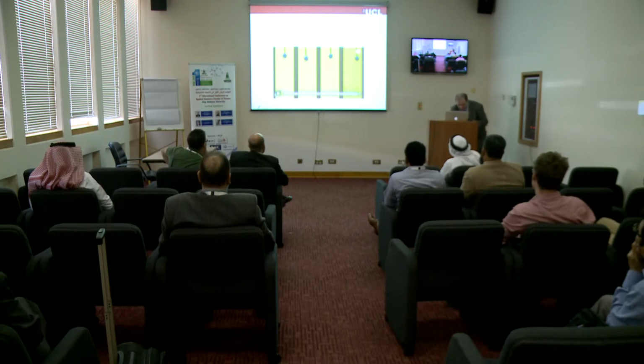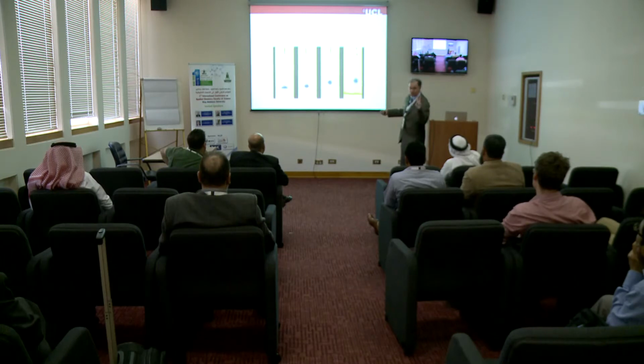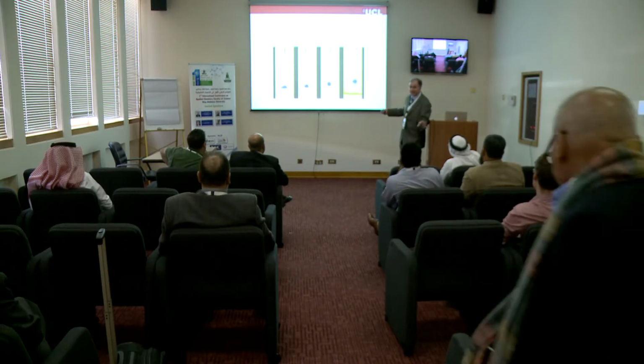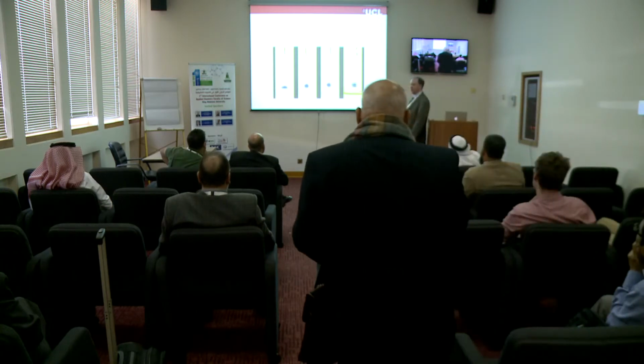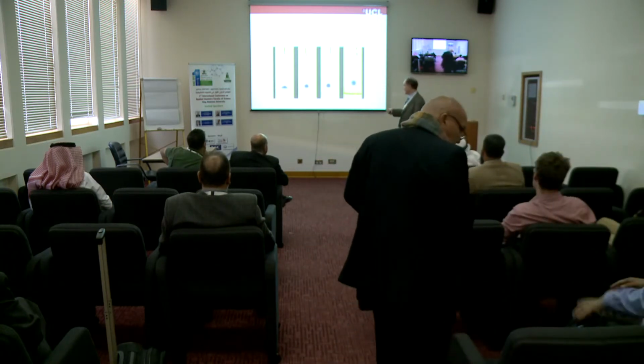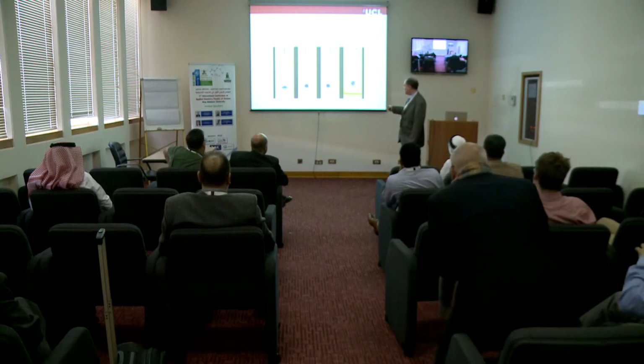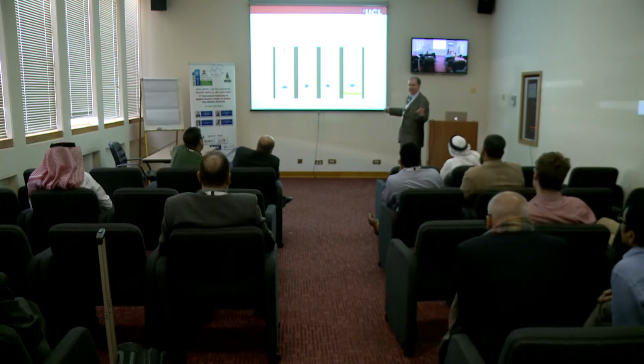Now this is my favourite, or one of my favourite videos. This is what happens when we drop water droplets onto different surfaces. This has a contact angle of 150, 1 bounce. This has one of about 160, there were 2 bounces. This one has a contact angle of about 170, there are 6 bounces on this surface. And this one, which is the champion, has a contact angle of 175. And you can see, if you were bothered to count, there are 13 bounces on the surface.